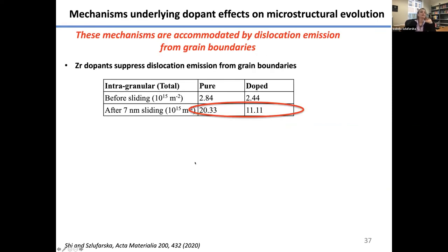So what's the mechanism of that? We have identified a number of mechanisms of grain growth in nanocrystalline aluminum, and the details are published in the paper. But most of these mechanisms of grain growth are accommodated by dislocation emission from grain boundaries. So we believe that this is an important clue for the design of wear-resistant nanocrystalline alloys. Specifically, you can see, adding zirconium, before sliding, these are the dislocation densities. They had comparable dislocation densities. After sliding, the doped sample had half of the dislocation density. And again, the dislocation emission is driving the mechanisms of grain growth that we found in our simulations.